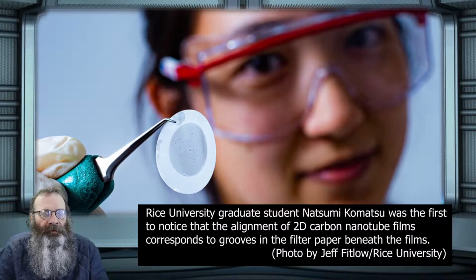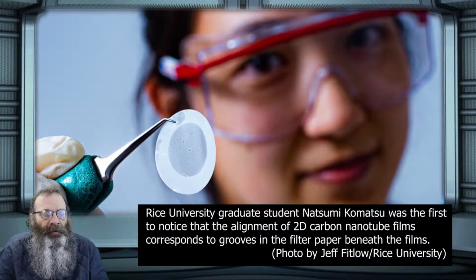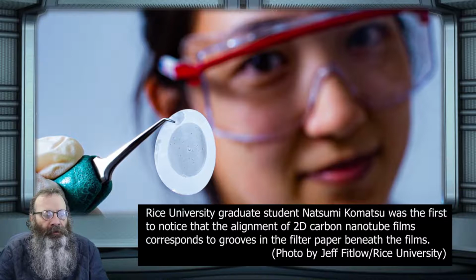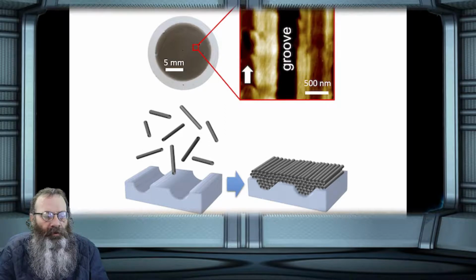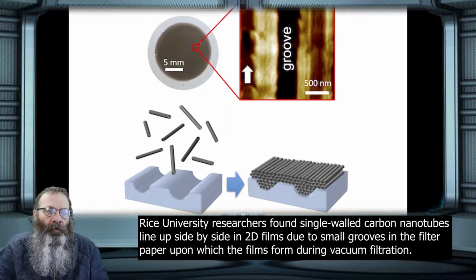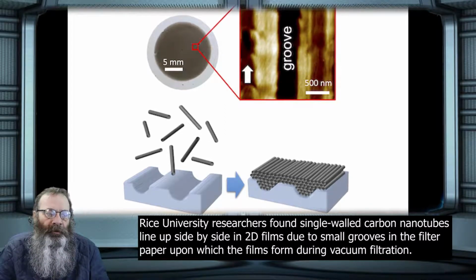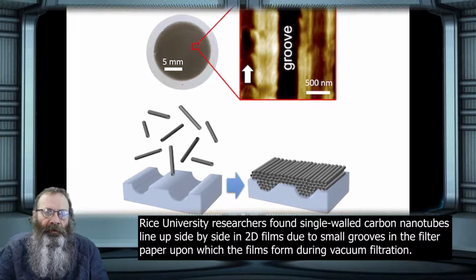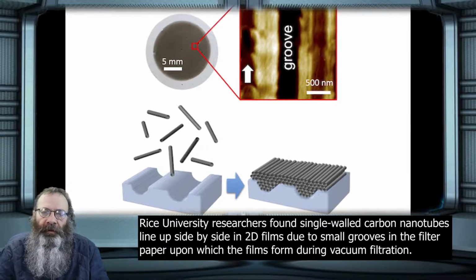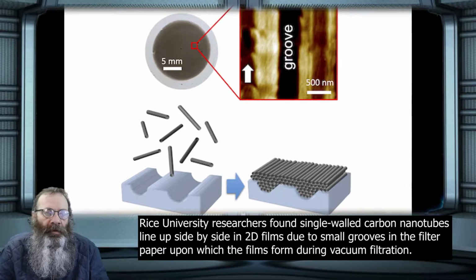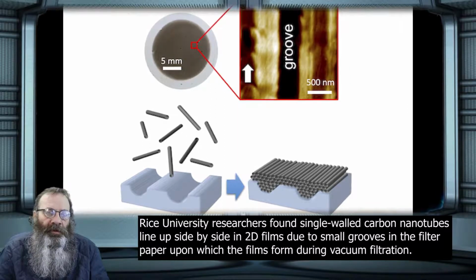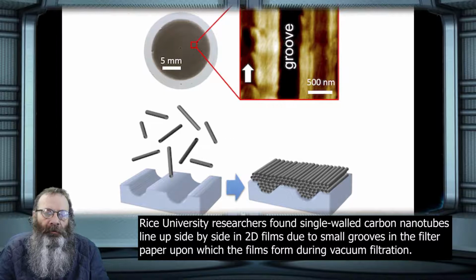Kono said the method is exciting because it brings a needed level of predictability to the production of 2D crystalline nanotube films. If the nanotubes are randomly oriented, you lose all of the one-dimensional properties, Kono said. Being one-dimensional is key. It leads to all the unusual but important properties. While Kono's group's films are essentially 2D, as much as an inch in diameter but just a few billionths of a meter thick, the individual nanotubes behave like 1D material, especially in terms of their optical and electronic properties.